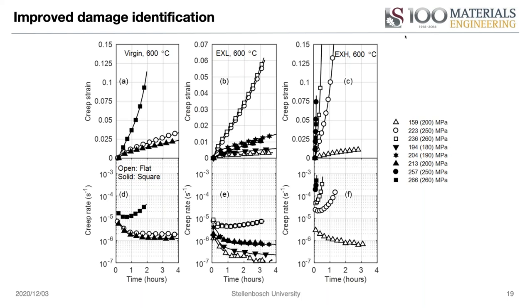Alternatively, we can plot these curves at different stresses rather than different temperatures. Here we have new material and service-exposed material. The difference from the previous slide is that in the previous slide each curve represents one sample—essentially all that data signifies only four tests. Whereas here, this includes eight different tests because our stress state is constant, not varying, and therefore we require different tests for different stress levels. Similarly to the previous slide, we observe that creep rates increase with stress between the low, high, and medium damage material and also the virgin material.